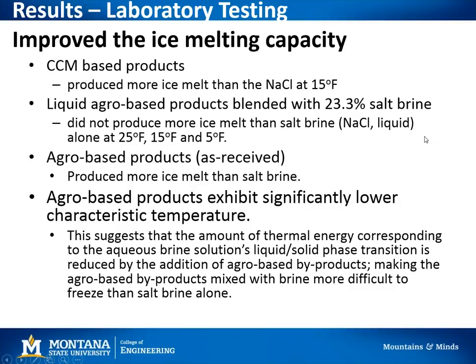And this suggests that the amount of thermal energy corresponding to the aqueous brine solution's liquid-solid phase transition is reduced by the addition of the agro-based products, making the agro-based byproducts mixed with salt brine more difficult to freeze than salt brine alone. And that's really where this theory of the cryoprotectant comes in, is that maybe these agro-based products actually prevent or halt the ice nucleation from occurring, and therefore prevent the ice bond from forming.